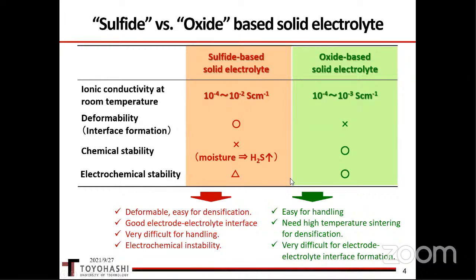On the other hand, the oxide-based solid electrolyte has slightly lower conductivity than sulfide, and generally high temperature sintering is needed for densification and reducing the grain boundary resistance, but it may cause an undesired side reaction with electrode materials. However, the chemical stability is very good, much superior to sulfide. This leads to easier handling.